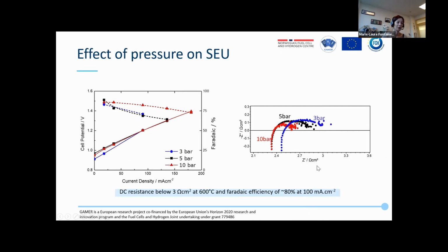I'd like also to show another example of how the material is affected by the operating conditions. Here you have the same type of figure, cell potential as a function of current density, this time for an SOEC operated at 3 bar, 5 bar, and 10 bar. You have here the cell potential, and here the Faradaic efficiency. The good news is that when we increase the pressure, the Faradaic efficiency increases, which is what we want. So that's the benefit of increasing the pressure.